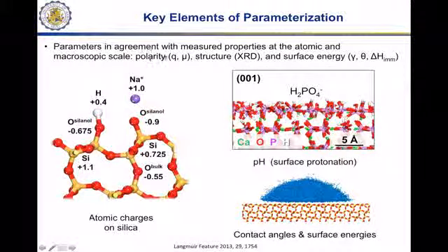In all these categories, including also for the electron density distribution, there are experimental data available, and we are really going to the experimental data because they are far less associated with uncertainties than, say, data computed from electronic structures, so especially electron densities and surface energies. And actually, this careful interpretation of the parameters in the end gives us an improvement in surface and interfacial properties by about an order of magnitude or so compared to previous models.